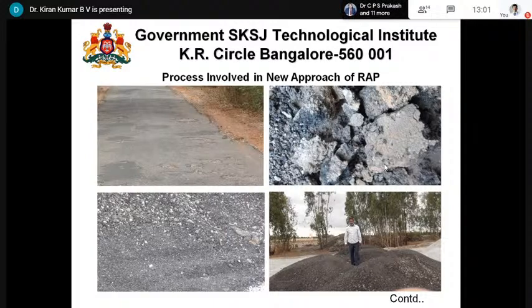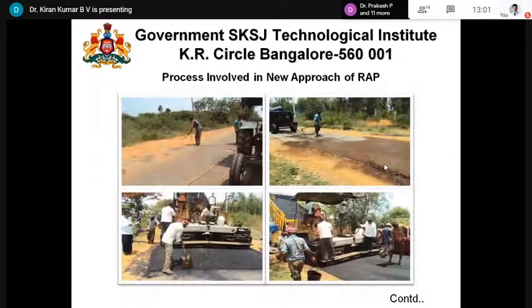This is our aggregate. You can see the lumps present on the sites are all virgin aggregate and stone chips and other things by the contractor. See the process involved in the new approach construction. We did not change anything, no fixtures, nothing. We have done all the back end calculation, back end work, and for our case it came up to about 139 rupees per square meter, 25 millimeter thick PMC, or 20 millimeter thick PMC. We got it as 139 rupees per square meter, and we did not change anything.